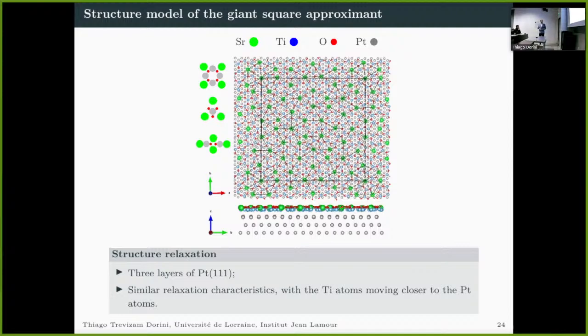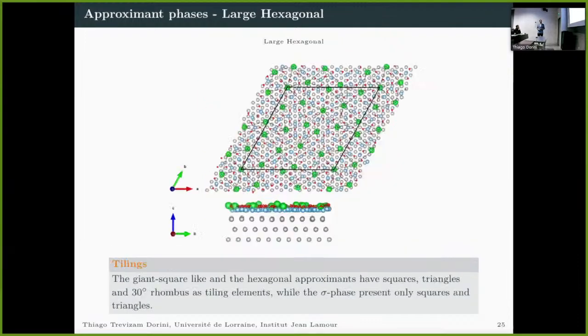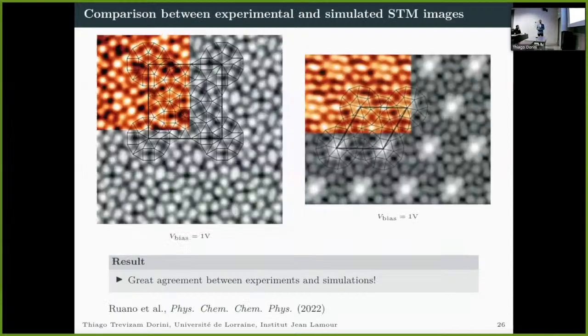And it has similar relaxation characteristics, as we see that the titanium atoms move closer to the platinum substrate and the oxygen and strontium atoms move upwards. The same analysis was done with another phase that was discovered, which we call the large hexagonal phase. It also presented 3 tiling configurations and basically the same relaxation properties as the other approximant phase. And it is interesting to notice that the difference between these 2 phases and the sigma approximant is that in these 2 phases there is the rhombus tiling configuration, and the sigma phase is a smaller phase and presents only triangles and squares.